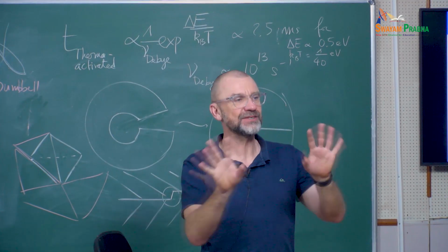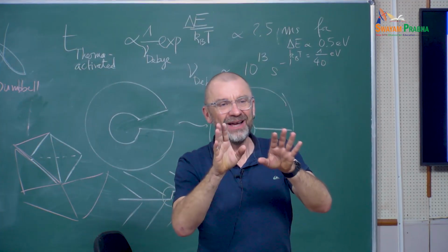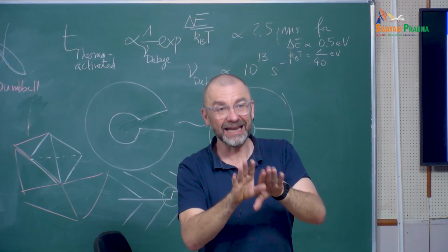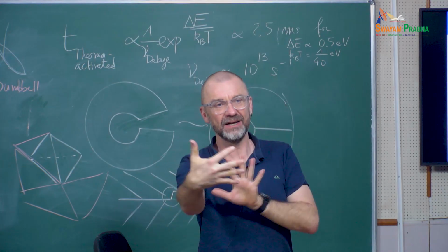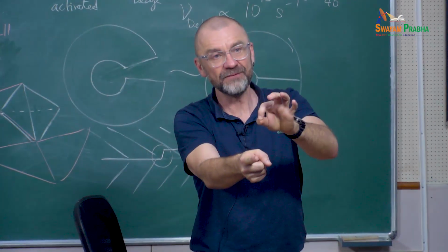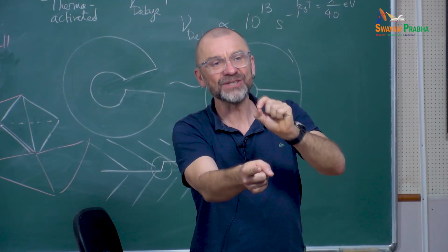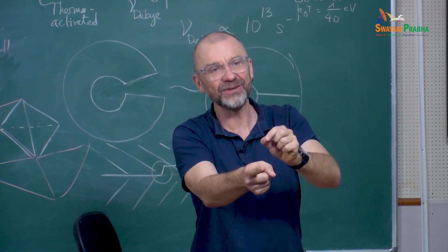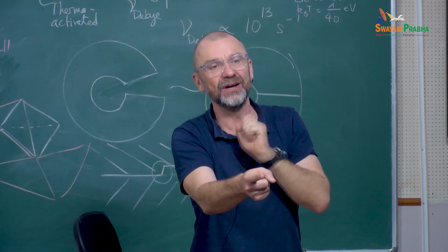With climb, so maybe it's too advanced for the others, but just for you, an issue also with climb and dislocations is that if I take a typical simulation cell with one dislocation and I put one vacancy, I will be much higher than the equilibrium concentration of vacancies.